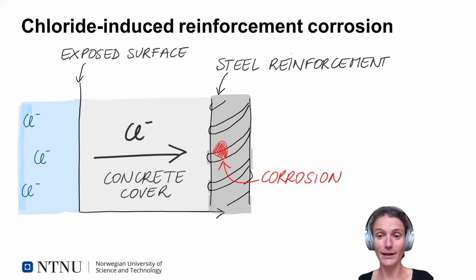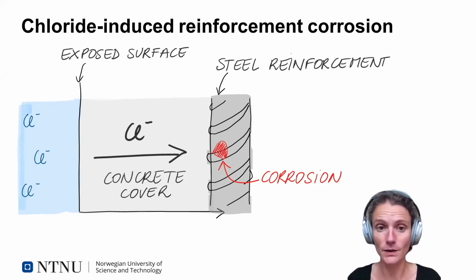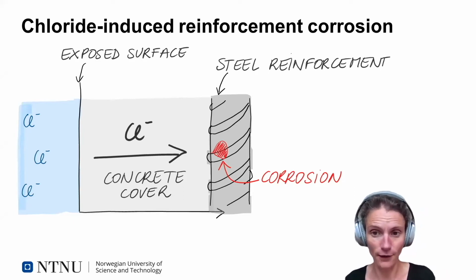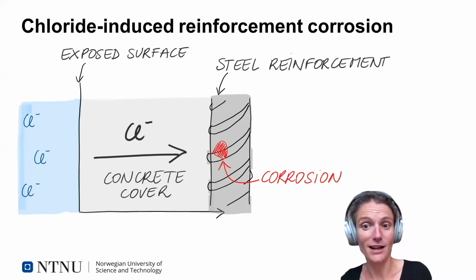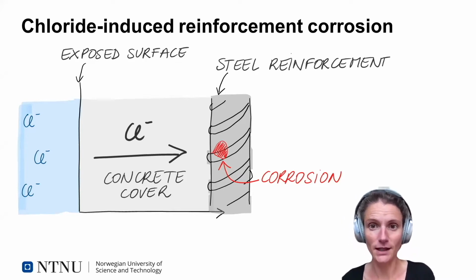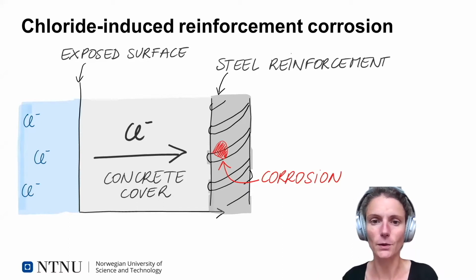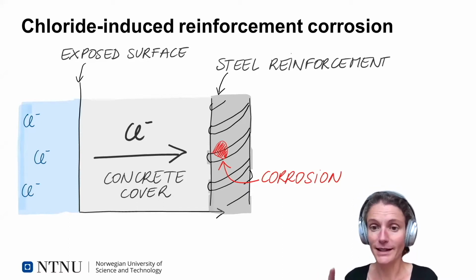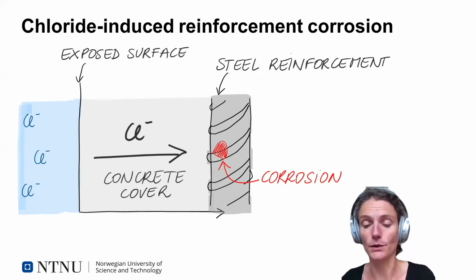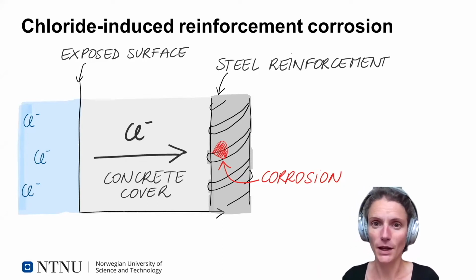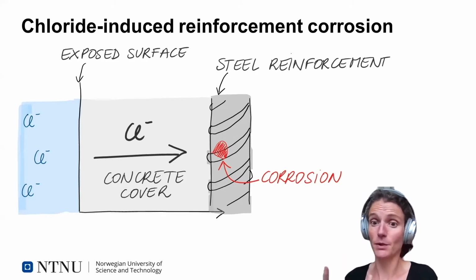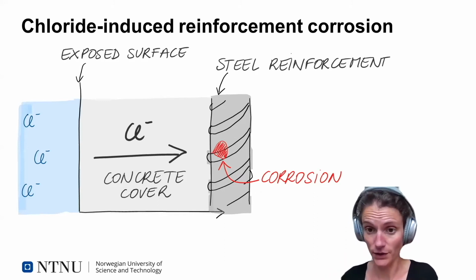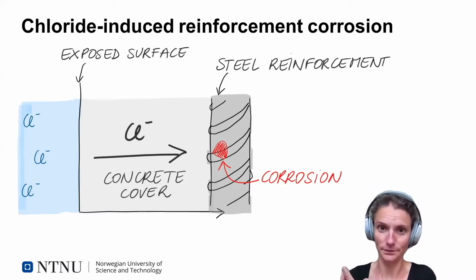What happens is that chlorides from seawater or the icing salts penetrate the concrete cover, and when they reach a sufficiently high concentration in the vicinity of the steel reinforcement, they'll cause corrosion. And it's this corrosion which will reduce the load carrying capacity of the structure and might lead to failure. So corrosion of steel reinforcement costs our society a lot, both in repair costs, but also potentially in having to demolish structures and build new ones.